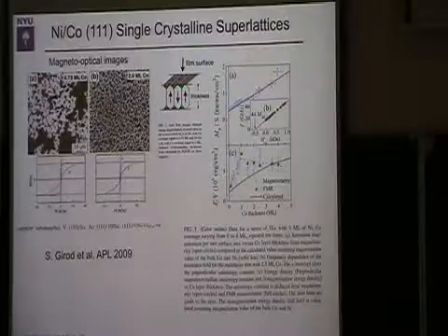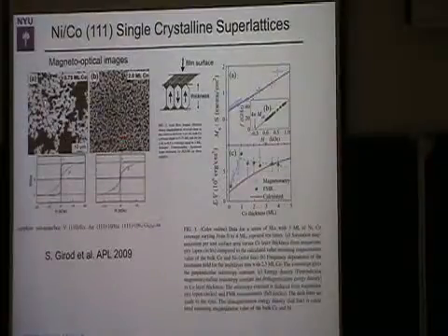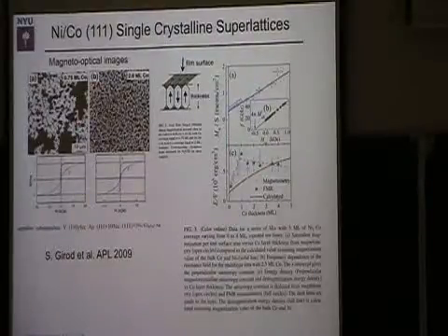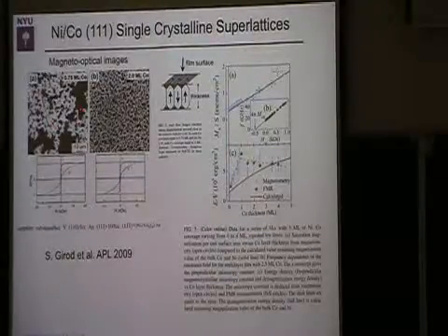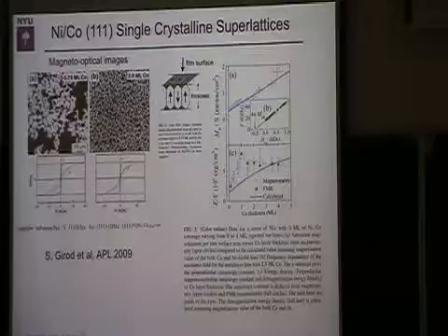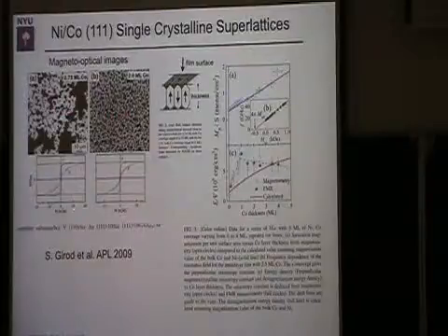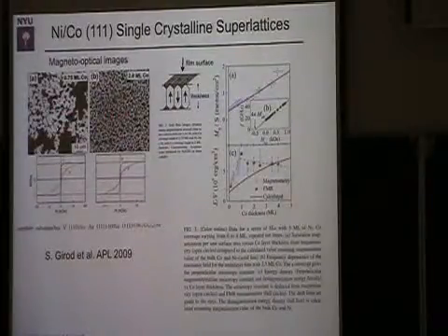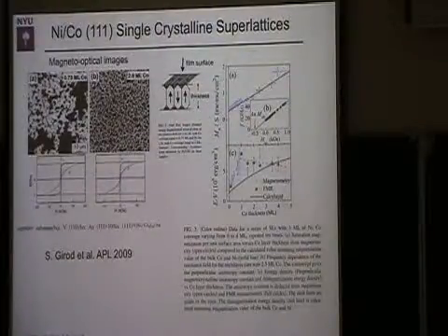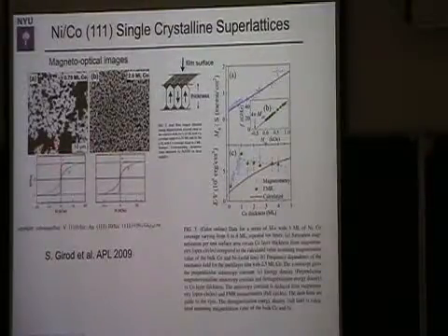Again, you're forcing the magnetization through something to try to reduce the magnetostatic energy, and you get these beautiful domain patterns and remnants, where the light is up and the black is down. These are magneto-optic images, so again based on the absorption of light, but this time at optical wavelengths, so the contrast is just an optical contrast. And so you can achieve situations like the Ising model. In these situations, you can have very strong anisotropy, on the order, as I said, of about 10 tesla. So you really have up or down domains. You're in this limit where Q is very, very large.